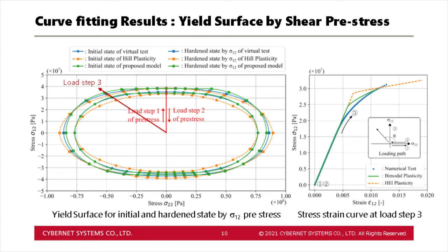Obviously, the fitting accuracy of the Hill's model is poor. On the other hand, our proposed model is showing better fitting results than Hill's model, both initially and after hardening state. The right graph shows the stress-strain curve and the load history of load step 3 shown in the left figure, where the Hill's model clearly shows excessively high yield stress.